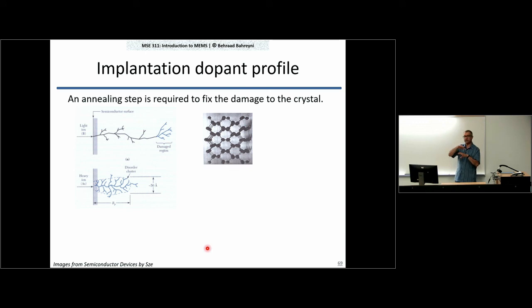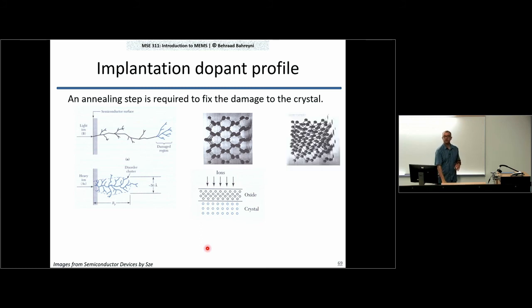After a while, you lose those nice little openings if you keep bombarding the surface of the crystal with these ions. But the other thing you can do is tilt the substrate a little bit. If you tilt your 100 wafer, you all of a sudden lose those long channels that you had deep into the substrate. It looks a lot more crowded, and your ion will stop relatively close to the surface where you want it. So this is one way of doing it.